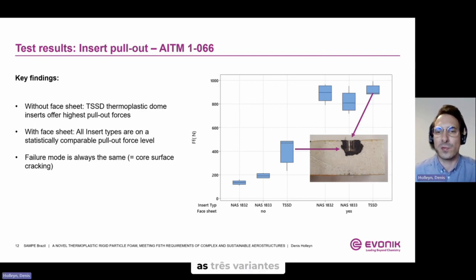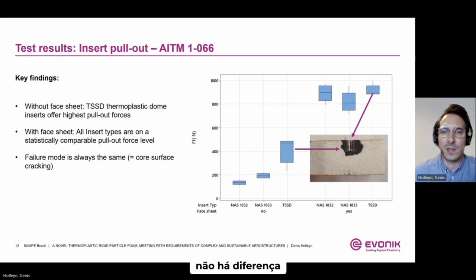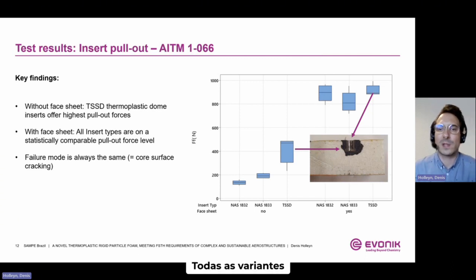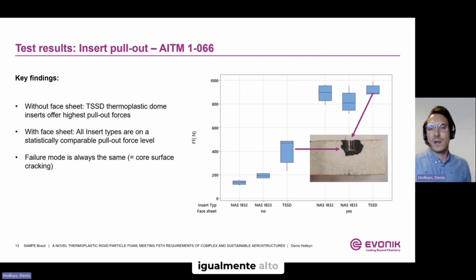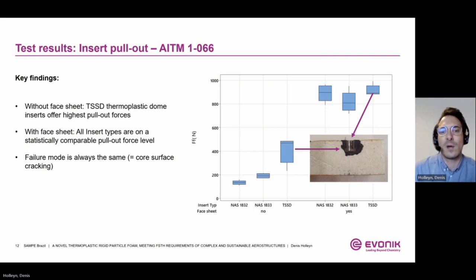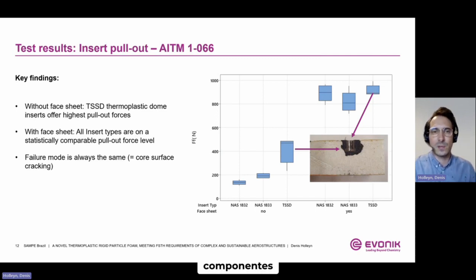When we look at the three variants including the face sheets on the very right-hand side of the diagram, there is no statistical difference between the insert types investigated. All variants perform on a similarly high level. All in all, we observed that the failure mode was always the same: a core surface cracking. This is the ideal failure mode for pull-out testing of inserts in sandwich composite components.